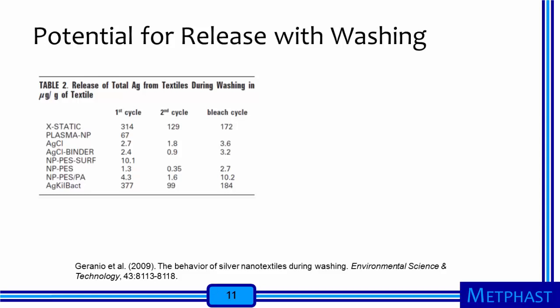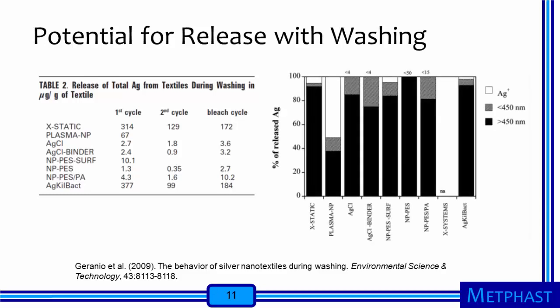Other authors have investigated the potential for releases of nanosilver from test fabrics during washing. Geranio and co-authors measured the release of silver from fabric containing nanosilver in a washing machine using a standardized test protocol. The table shows that substantial releases of nanosilver can occur and that the amount released decreases during a second washing cycle. Not surprisingly, the largest releases on an absolute basis were for fabrics that contain more silver to begin with. In this figure on the right, the releases during the first washing cycle are separated into particles larger than 450 nanometers, particles smaller than 450 nanometers, and silver ions.